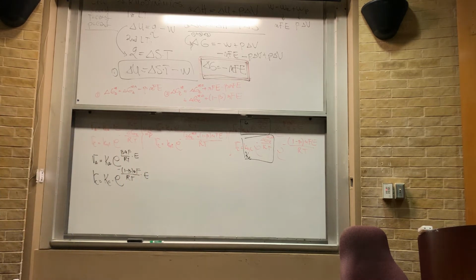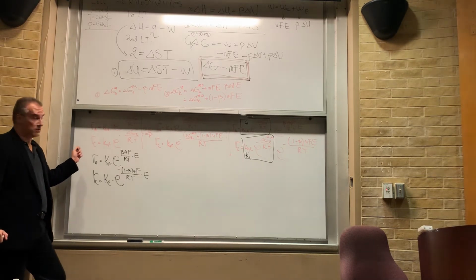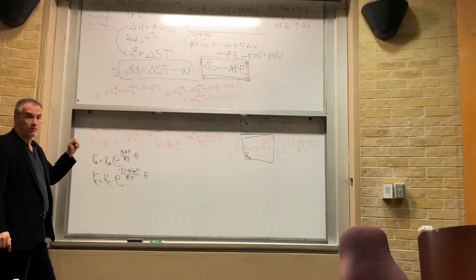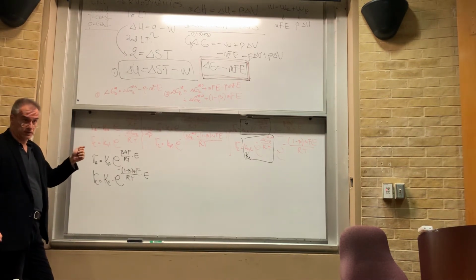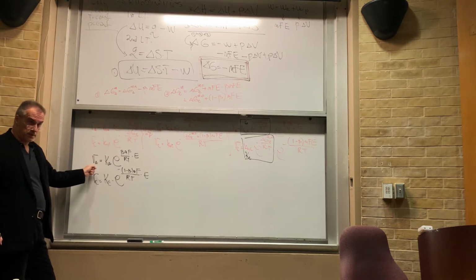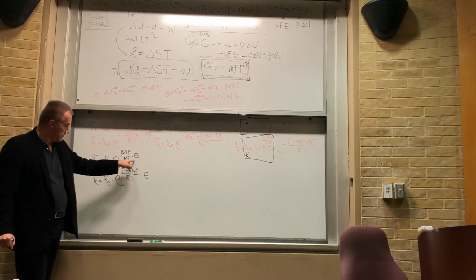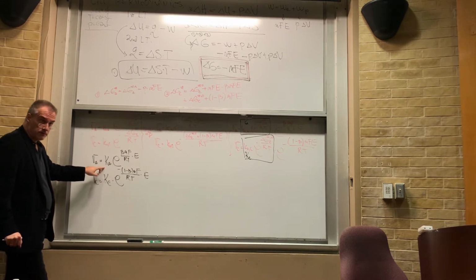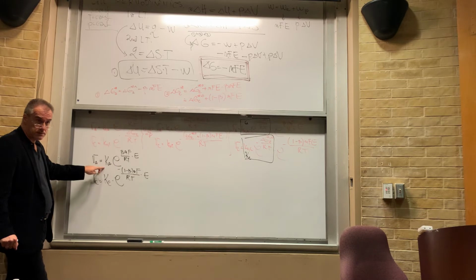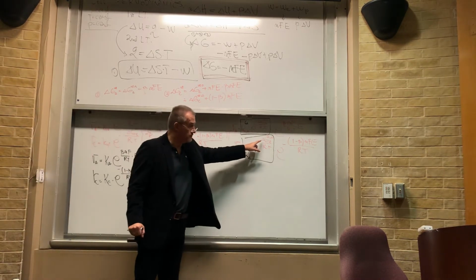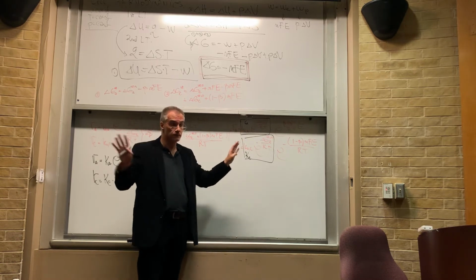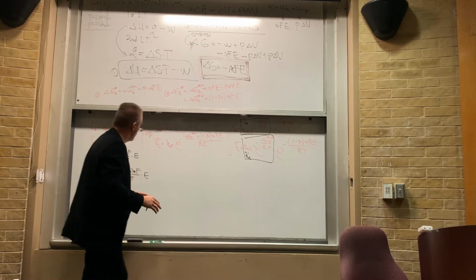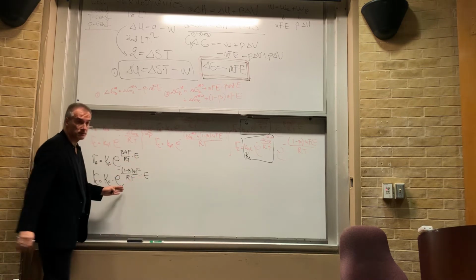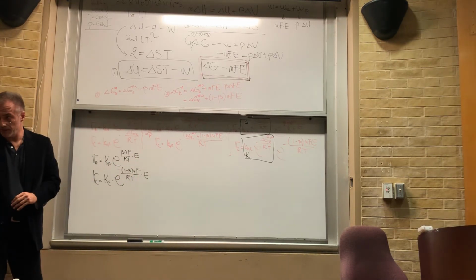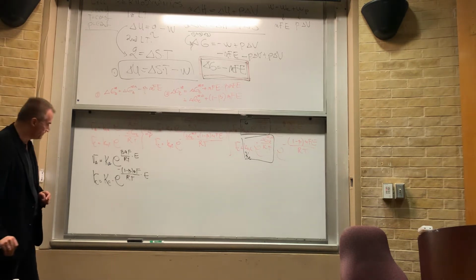Okay. So obviously what is really important is that now when we have potential across the interface, when we are driving the reaction with application of potential, the rate is dependent on this potential, obviously, and also the pre-exponential factor is related to these chemical constants, which in essence contain the free energy of the activated complex without any field applied, right? So the correction for the field is in these exponential terms here. Everybody clear with that? All right. Beautiful.